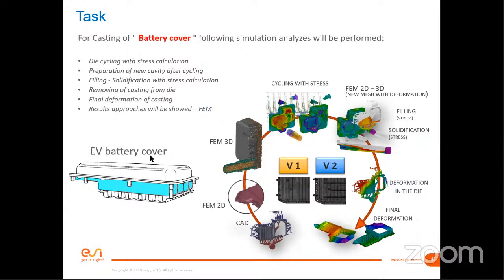It's about a battery cover for an electric vehicle. So it's a kind of modern part, as you can say. The blue part, not exactly the one, but a very similar one, is shown here on this graph, where we started from the CAD, performing many simulations of, for example, cycling with stress, then getting a new kind of shape of casting after the thermal expansion of the die, and then standard filling, solidification, calculation of deformation and stresses inside the die, and then what happened after the casting is ejected from the die. This is the whole process, and only this can be somehow considered as a reference for the process setup.